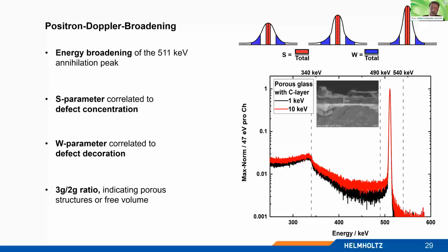In the graphic, on the right side, there is the 511 keV energy peak, which gets broadened if you have fewer vacancies in your system. So we calculate the S and W parameters. The S parameter is more or less correlated to the defect concentration, and the W parameter is correlated to the defect decoration. This leads to more and more information about your material and the atoms surrounding your vacancies, for example.